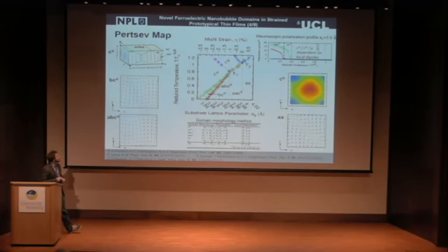So these are the results we get. This is using a 10 by 10 by 10 simulation cell, so quite small, but for the thickness of the film, that's actually good agreement because our model also satisfies the Kittel scaling law to do with domain thickness. So this was an ideal size to use and has also been used in the literature.